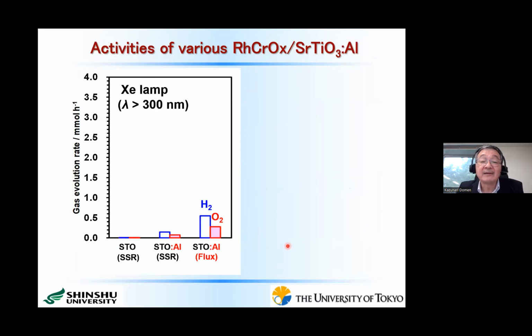Here I compare the activity of the overall water splitting reaction. Again, in this case, we modify only by hydrogen evolution co-catalyst. And the light source is a xenon lamp, longer than 300 nanometers, that includes the UV light. Here I show the activities. When we use a stoichiometric strontium titanate, in this axis, millimole per hour, the activity seems to be almost negligible. But as I showed previously, we can get hydrogen and oxygen evolution in 2-to-1 ratio.